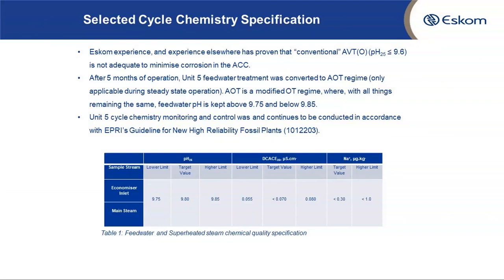Conventional AVTO, this is in Eskom's terms. At Eskom, we referred to AVTO at pH equal or less than 9.6 as conventional, since all stations at Eskom that are operating on AVTO, there is none before Medupi and Kusile, the new power stations, that was operating at a pH greater than 9.6. That is why we term this AVTO as conventional, even though when you look at the IAPWS, you will see that the pH range for the AVTO is still about 9.2 to 9.8. So this conventional is in Eskom's terms.